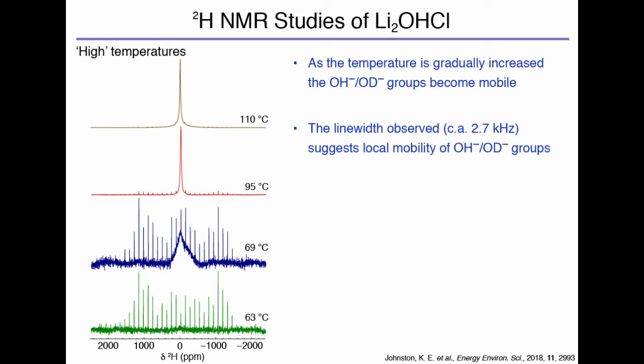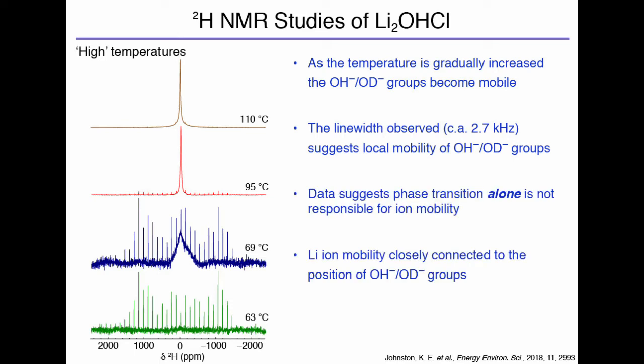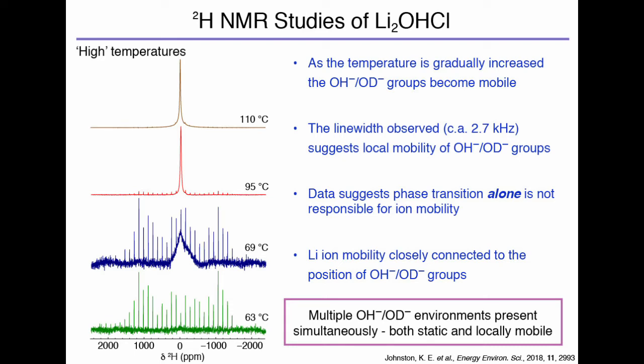So what that's telling us is you don't just get a complete change of the structure. There's a gradual process occurring, and you actually have the coexistence of two different proton environments, one that's stationary and one that's moving. So what's causing that? Quite interestingly, it seems to suggest that the phase transition alone isn't responsible for this superionic conductivity as it's been described, and also that the lithium mobility is related to the proton mobility, which I'll come to in a second. But it's really interesting that the NMR was able to indicate that we have the presence of these two different proton environments, one that's static and one that's moving.